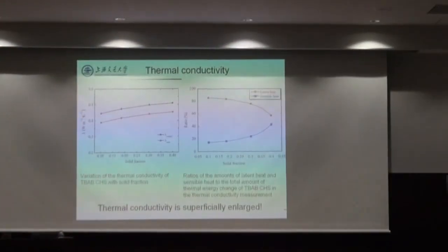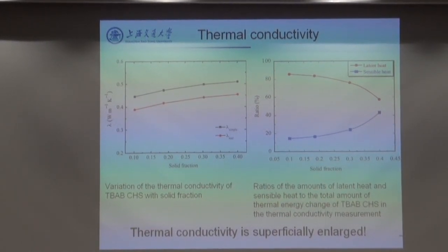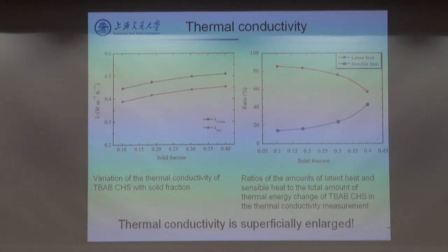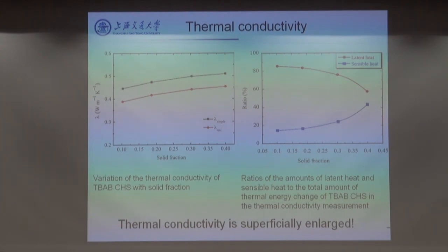Question: The thermal conductivity of TBAB-CHS that you showed was 0.4 W/mK. Is thermal conductivity not an issue for practical application? Answer: In this particular application, thermal conductivity is not a very critical issue for pump-driven systems. However, you need to know the thermal conductivity of the solid phase to evaluate the heat transfer performance accurately. This is also important for researchers working with carbon dioxide hydrate as a solid phase who need fundamental information about different hydrate phases.